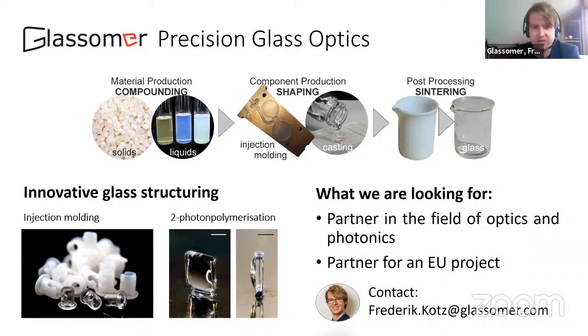As we found, we did already diffractive optics and refractive optics with that, diffractive optics with a layer height of 250 nanometers, for example, using thermal nano imprint. Happy to discuss that further, where you need an extremely precise shrinkage compensation, and that's quite easy because it's an isotropic shrinkage. Okay, we should keep talking.